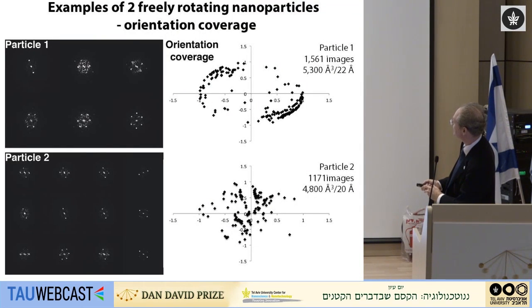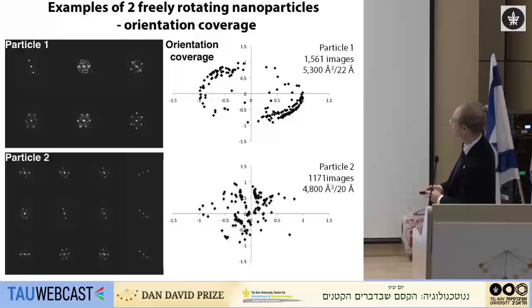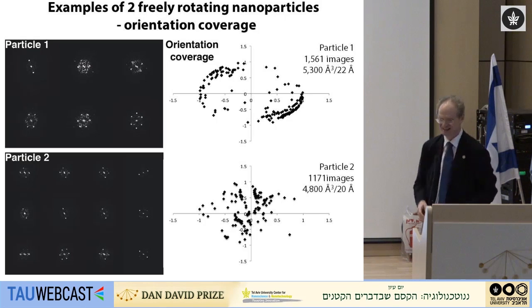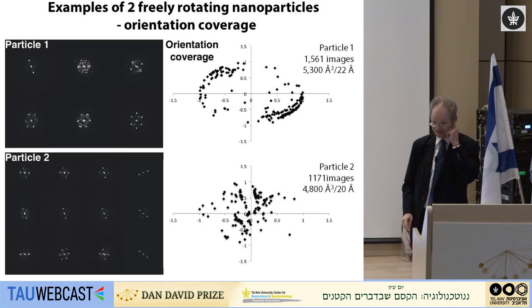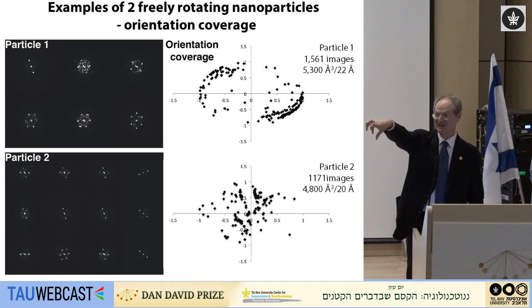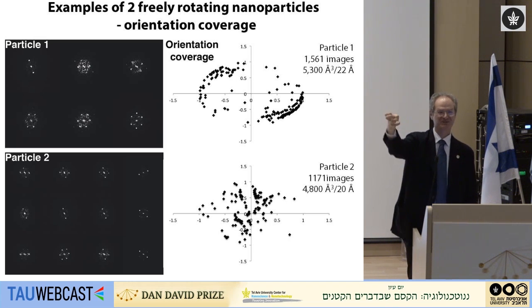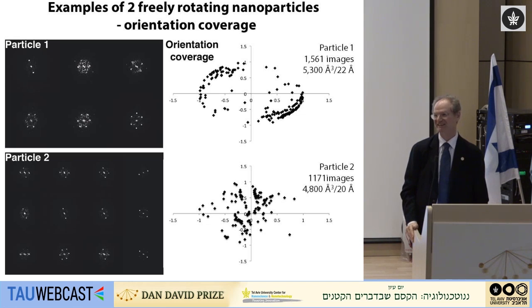And so this would be an example, for instance, of a single particle, and these would be diffraction patterns where the background has been subtracted, and what you'll see is that we observe many different orientations. And in the limit where we've collected, say, 1,000 or so of those kinds of diffraction patterns, we actually now have enough information to go back and obtain the electron density of every position inside the crystal.